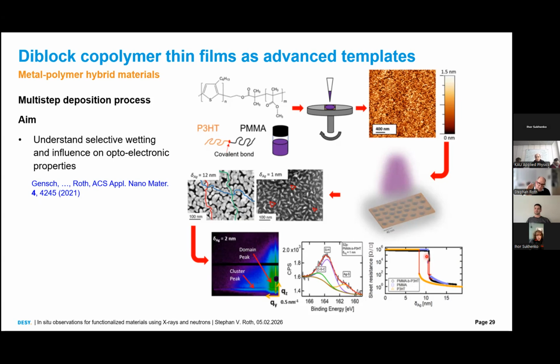Typically for these, we have already proposed to include a sputter chamber into a neutron beamline. But then we would do what is called self-sputtering. You deposit a layer and you measure for 1 hour. You deposit the next layer, you measure for 1 hour. You have to make sure that the cluster layer doesn't grow or change in that time between two depositions. Here we really do it in situ with X-rays during deposition.